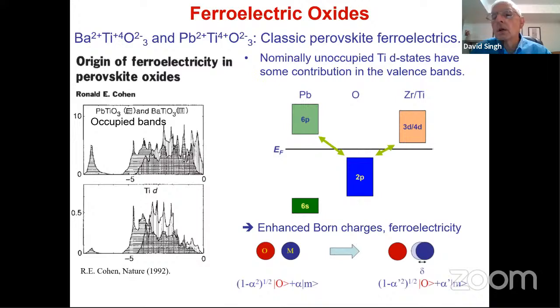materials. And the material that used to be commonly used was a material called PZT. It's an alloy between lead oxide and zirconium titanium oxide. It occurs in a certain structure called perovskite. Anyway, this is a Nature paper that was published by Ron Cohen in 1992, where he explains the performance of those materials. And it's based on covalency between oxygen and these cations, these nominal cations, lead and titanium.